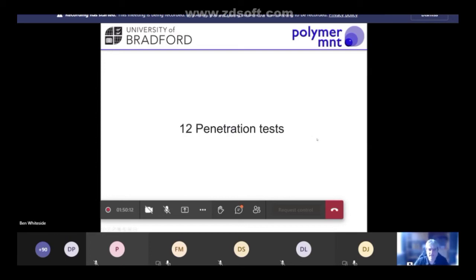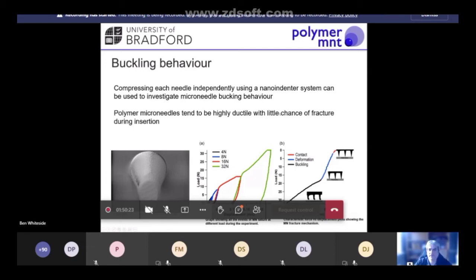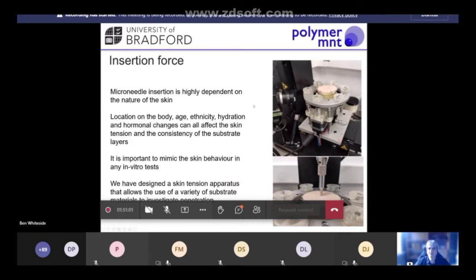And I've briefly hinted at penetration tests. So we do lots of work with porcine models for looking at the penetration behavior of various microneedle arrays. What we would generally do with a new microneedle geometry is use a nano indenter with a flat punch to investigate the microneedle buckling behavior. So we can compress each microneedle in an array, take force measurements from that, and look at the nature of the failure of the microneedle. So make sure it doesn't fracture and then get left in the skin. And with polymer microneedles, we generally see very good behavior. They tend to deform in a highly ductile manner, which means we would be unlikely to see broken needles in the skin during use.